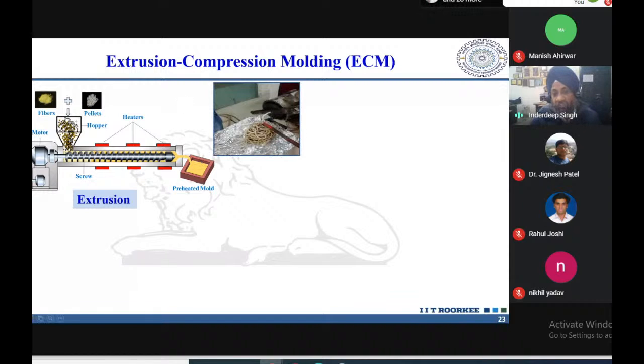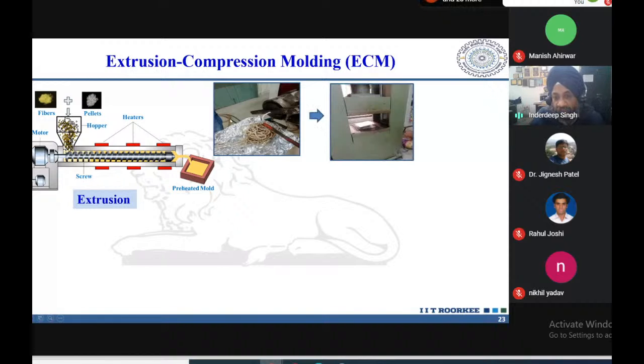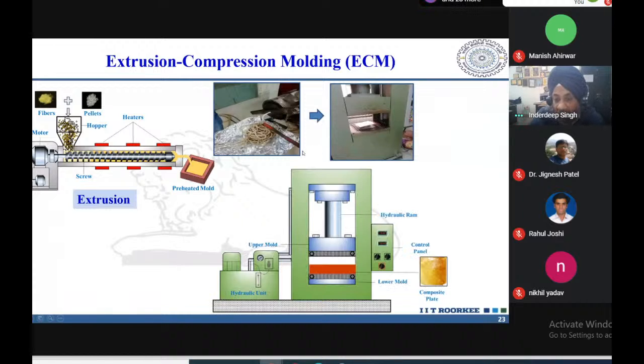You can see here, this is the actual picture, the material coming out from the die of the extrusion machine, and it is getting collected. Here it is just being collected, but normally once we have to do extrusion compression molding, we collect it in a mold, and then that mold is transferred to the compression molding machine. This is our industrial scale compression molding machine, and once the plate is ready, it is taken out by opening the two halves of the mold.